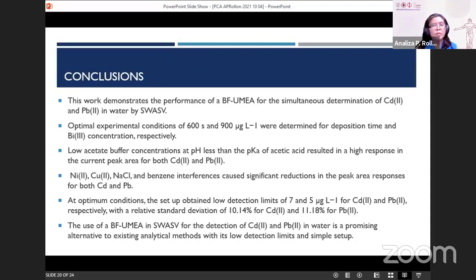So as conclusions, this work demonstrated the performance of the bismuth film ultramicroelectrode array for the simultaneous determination of cadmium and lead in water by square wave anodic stripping voltammetry. The optimal experimental conditions are 600 seconds and 900 micrograms per liter for deposition time and bismuth concentration. And a low acetate buffer concentration at pH less than the pKa of acetic acid resulted in a high response for the current peak area for both cadmium and lead.